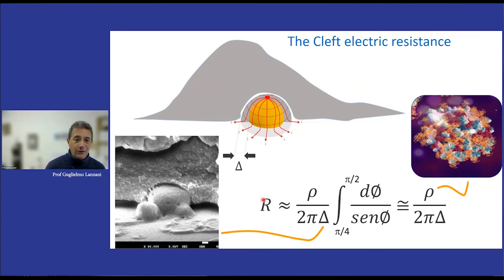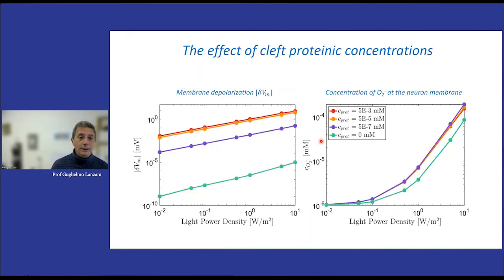So the result is the following. This is a simple calculation of the resistance of this geometry, and the Ohm law, right? And you see that the electrical resistance depends on the resistivity of the medium and has an inverse dependence on the thickness. So because the thickness is very small and the resistivity of a protein medium is very high, we expect the electrical resistance here to be very high, which means that the nanoparticle is establishing a giga seal with the cell. And now, if you do the calculation of the membrane depolarization due to the electrostatic effect, what you see here is that increasing the concentration of proteins, you go higher, from green to orange, and you see that the depolarization becomes much larger.